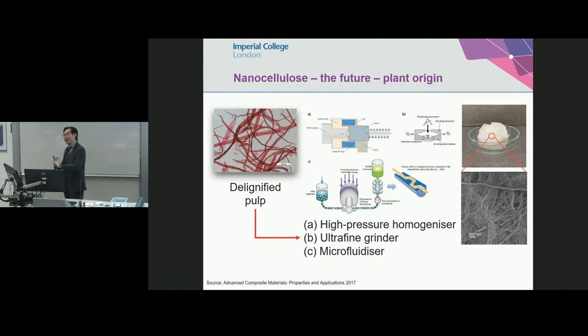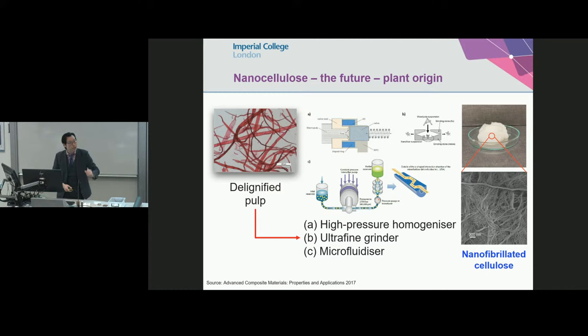For those plant-derived cellulose, we typically call them nanofibrillated cellulose. That's a picture of that, approximately 10 to 50 nanometers in width, and it can be several micrometers in length. Length is quite a difficult thing to quantify. This is how it looks. The starting pulp is quite dry and fibrous. Once you put it through the homogenization process, you get a creamy-like material that has this nanofibrous texture underneath.